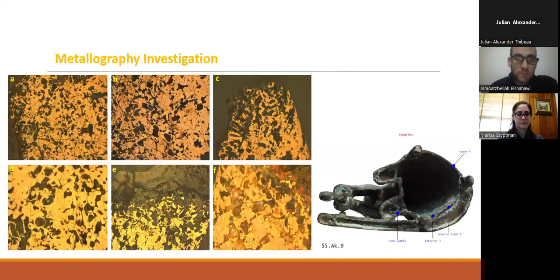Peter Myers, who is a conservation scientist at the LACMA Museum, and I did a microstructure study on the cat. Optical micrograph of microstructure showing dendritic shape cast areas of metal core, grains of copper-rich phase, lighter areas, as we can see here, surrounded by lead-rich phase, lead segregation with the gray and black areas, and intergranular corrosion of red color, cuprite. This gives us a high probability that the cat is authentic.